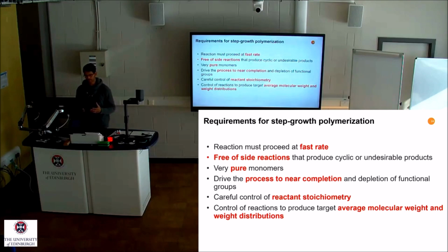You have to be completely free of any side reactions, so, for example, you have to take a pure monomer. Whenever you have any small molecules, you have to remove them as soon as possible, because those small molecules or impurities can create side reactions, which can result in really small oligomeric polymers, or not the proper properties of the polymer.